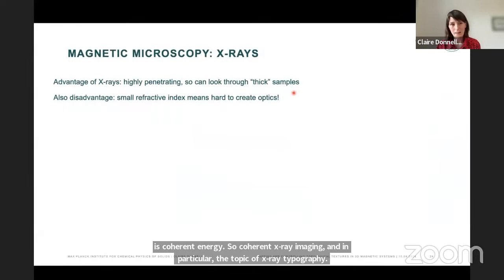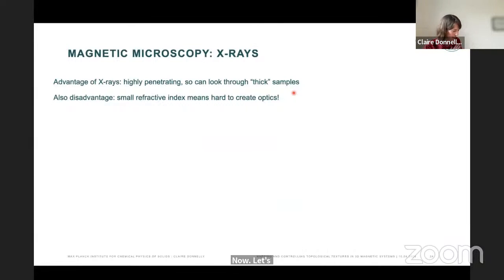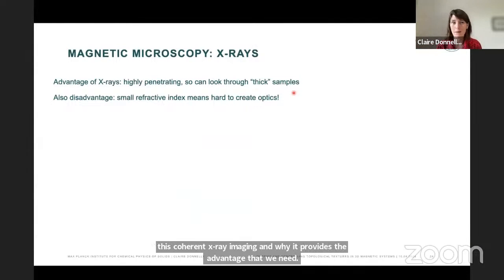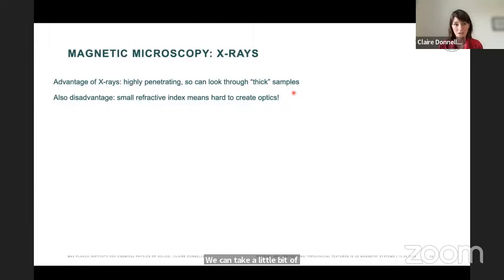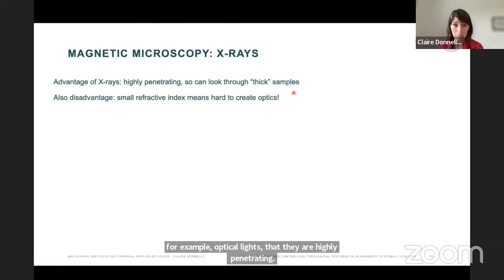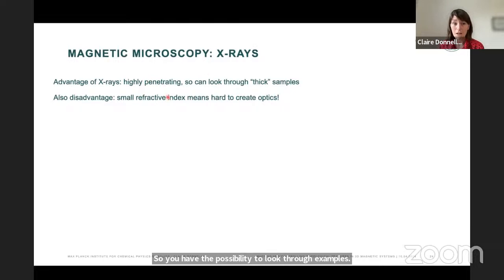Now, in order to understand the context of this coherent X-ray imaging and why it provides the advantage that we need, we can take a step back and consider magnetic microscopy in general. We, of course, have the advantage of X-rays compared to, for example, optical light, that they are highly penetrating. So you have the possibility to look through thick samples. But we also have a disadvantage: this small refractive index means that it's hard to create the optics to really take advantage of the small wavelength of the X-rays.